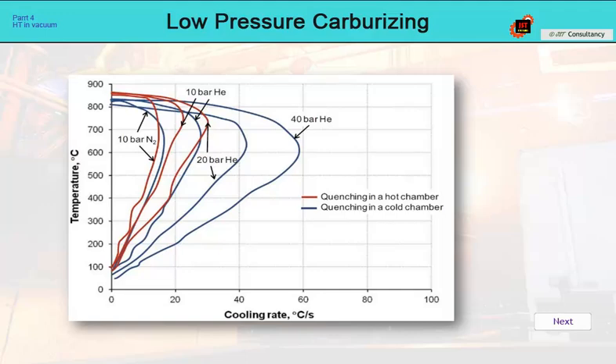This diagram shows the cooling rates for nitrogen and helium in single-chamber furnaces and in double-chamber systems with a cold chamber for quenching. They show that the use of single-chamber systems is very impractical, because with each load, we cool down not only the parts and baskets, but also the entire hot zone. So, we must have at least 2 chambers, one for heating and carburizing, and the other for quenching. The efficiency of cooling in a gas stream will increase by an order of magnitude, but we are still not at the level of oil quenching.